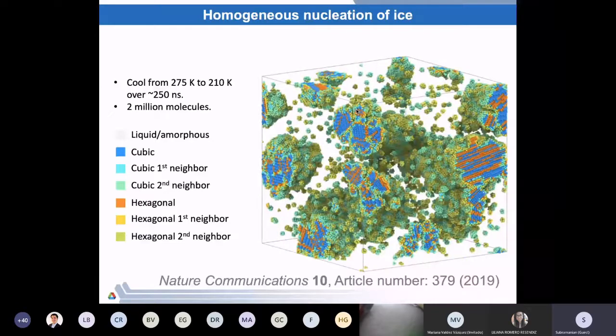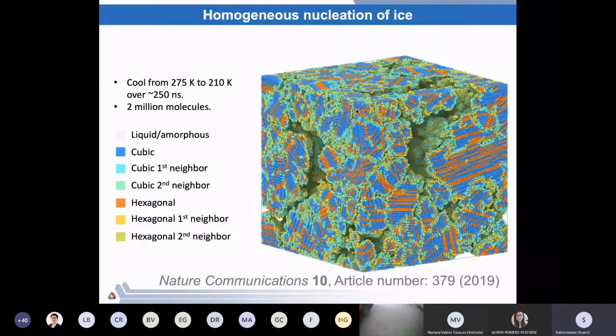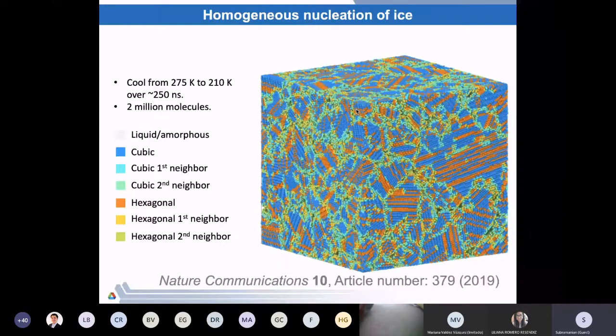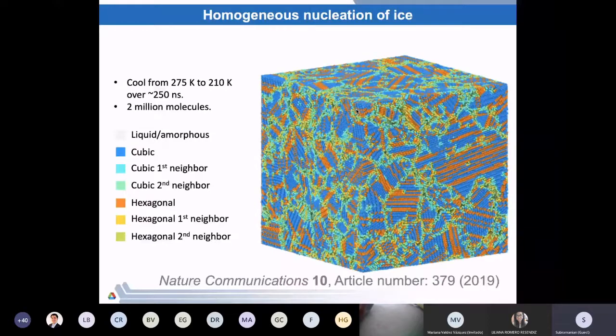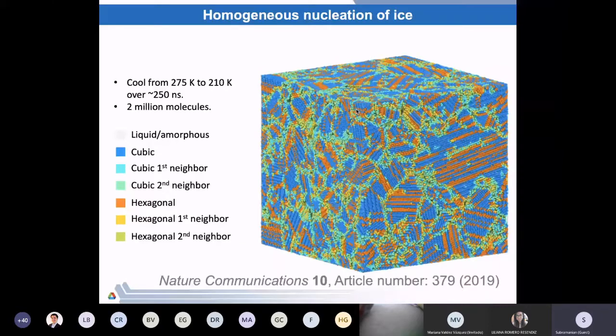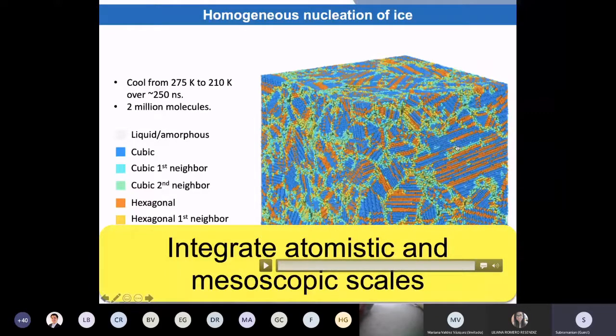So if you take supercooled water that is at 210 Kelvin, you can actually not only watch the nucleation of ice, but you can also look at how these ice grains form and grow, and features such as how the stacking disorder ice actually forms. And there is a very intricate Ostwald ripening process that happens in the case of ice for the coarsening of these ice grains, that is different from what you typically see in the case of metals and ceramics, where the grain growth often happens by just the grain boundary migration.